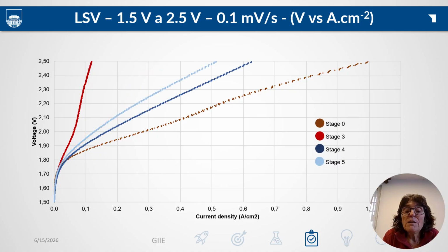In this figure, we can see the effect of the regeneration treatment. The curve in stage 4 partially recovers the performance of the baseline stage. This tells us that most of the performance loss in the Nafion 1110 assembly was due to reversible contamination that sulfuric acid can wash out.